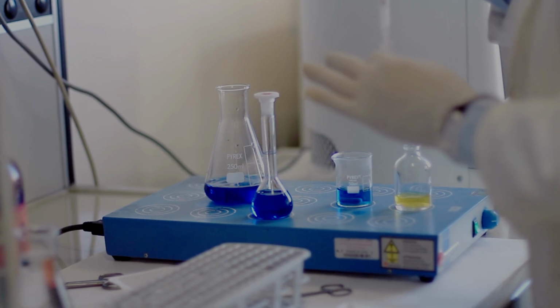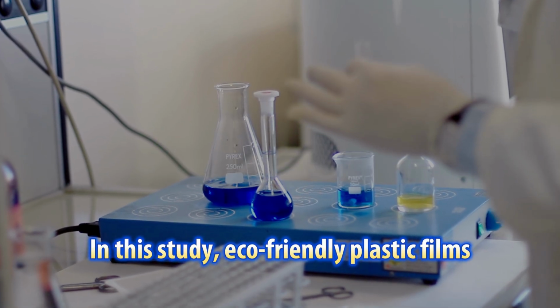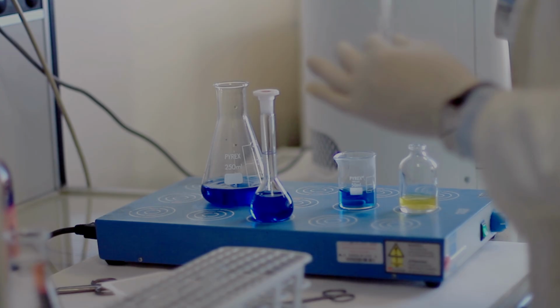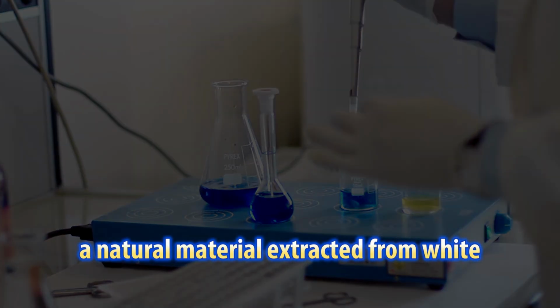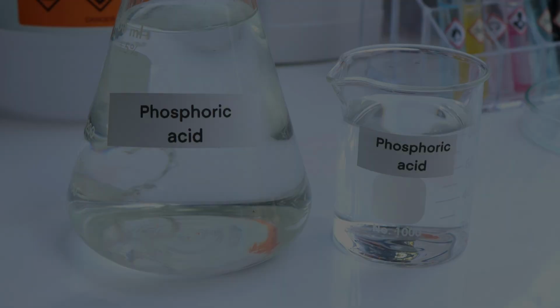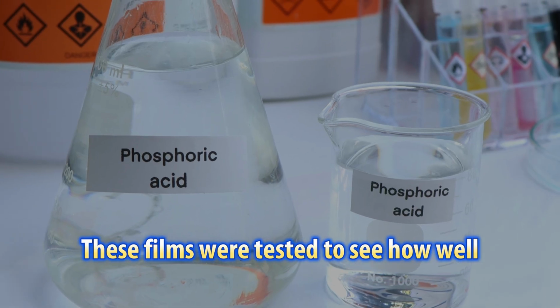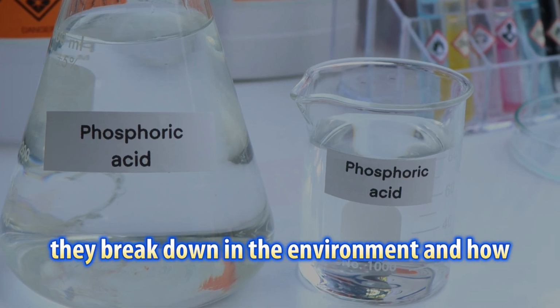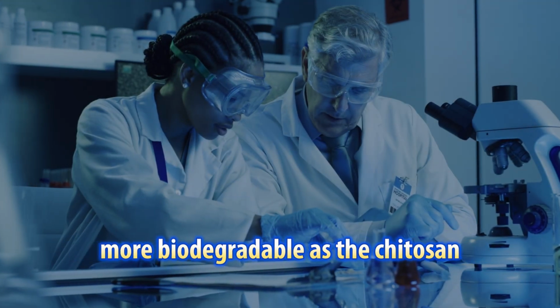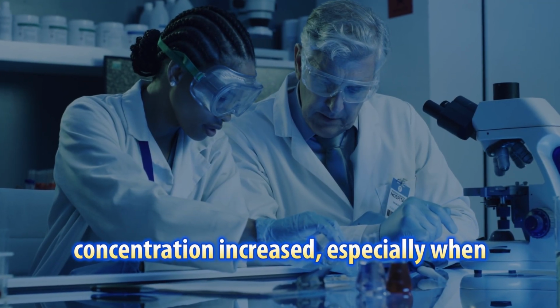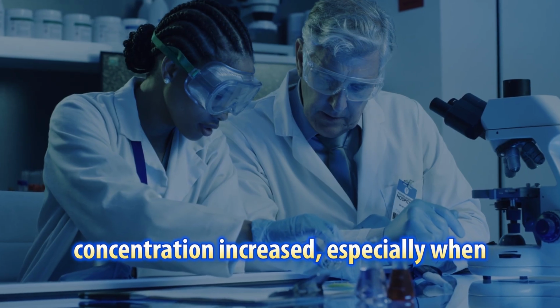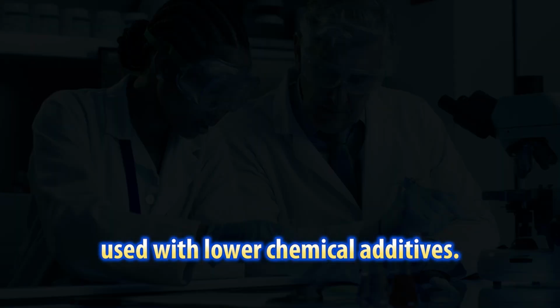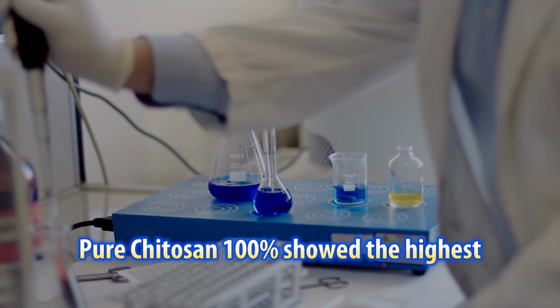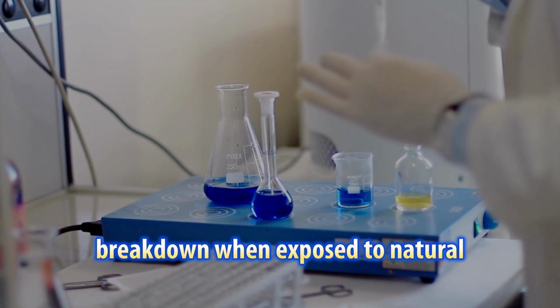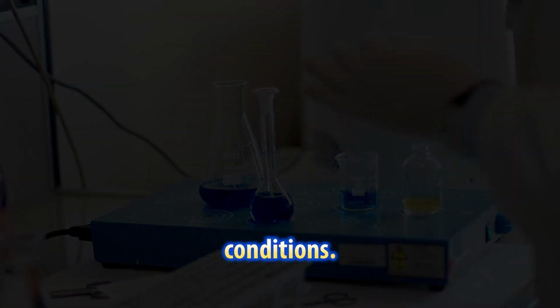Conclusion. In this study, eco-friendly plastic films were made using chitosan, a natural material extracted from white shrimp shells. These films were tested to see how well they break down in the environment and how strong they are. The results showed that the films became more biodegradable as the chitosan concentration increased, especially when used with lower chemical additives. Pure chitosan, 100%, showed the highest breakdown when exposed to natural conditions.